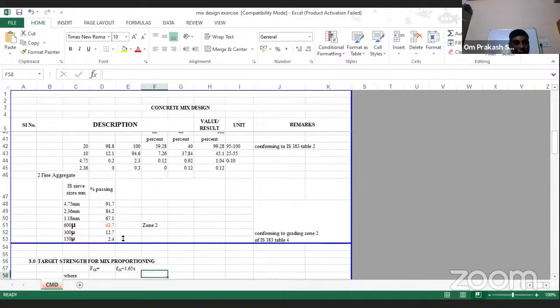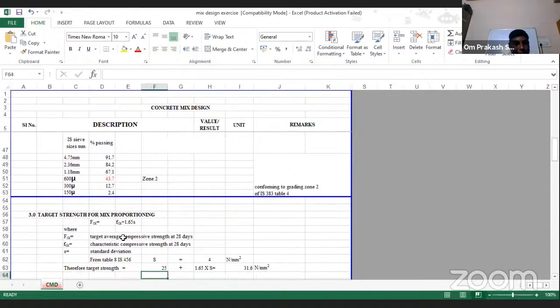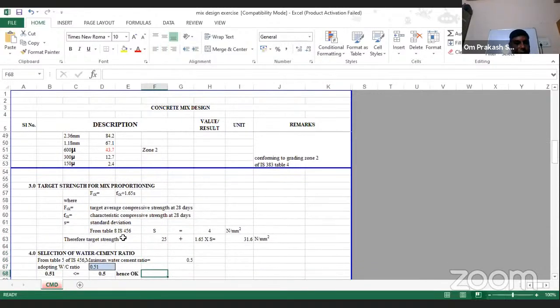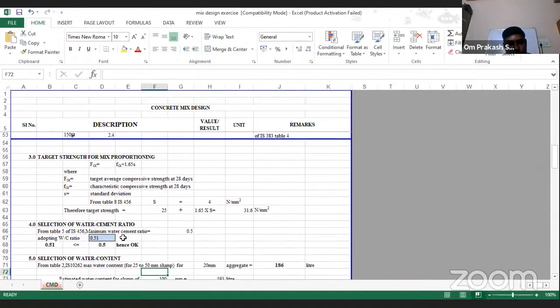After that, now we will go with the target strength. So target strength is our fck plus 1.65 into S. The value of S for M25 is given as 4 in IS 456. So what we have to do? 25 plus 1.65 into 4. That is 31.6. It is our target strength.